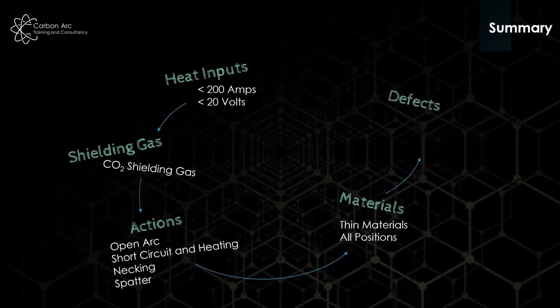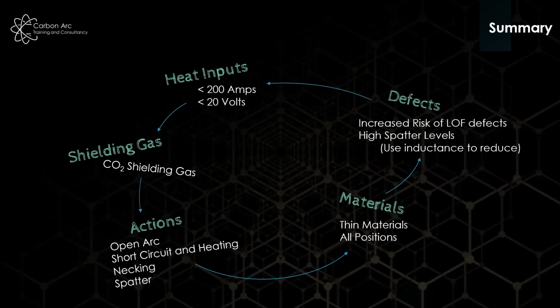But because of that low heat input, we have the risk of lack of fusion type defects, whether that be lack of sidewall fusion, penetration, or lack of root fusion. There just sometimes isn't enough heat there to make sure that everything melts in all of the time. But we gain the all positional thin materials benefits that make this process very good for some applications.